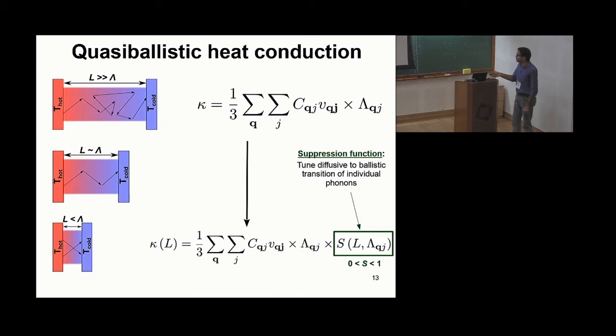Basically, what I'm saying is you can do the experiment at different L's, and create a set of independent equations, because S is independent of any of the other properties here—it independently depends on L. So you can tune S by just changing L, which means when you change L, you create a number of equations of this form. If you have a sufficiently large number of L's, you can in principle invert this function to get lambda. So you're transitioning an ill-posed problem to a relatively more well-posed problem.